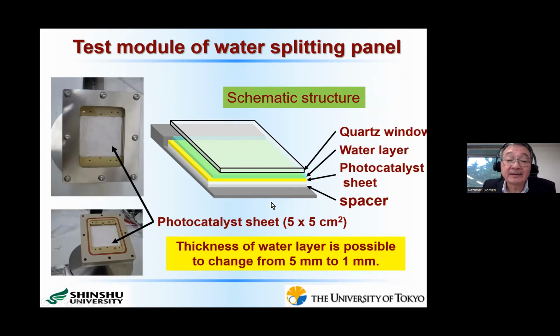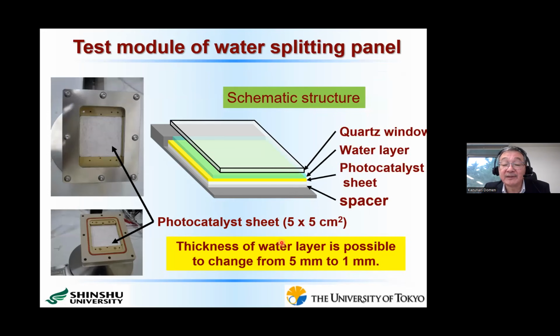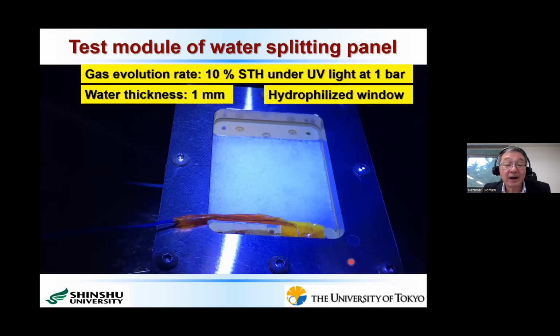And based on this kind of photocatalyst sheet, we constructed the water splitting panel. This is the smallest water splitting panel. The size is about 5 centimeters times 5 centimeters. But in this case, we can control the thickness of the water layer from 5 millimeters to 1 millimeter. Now let me show you only one example.